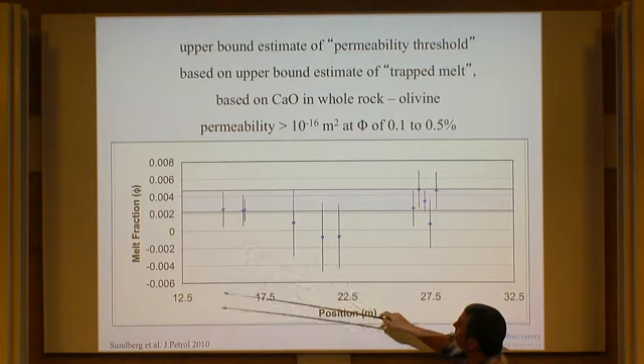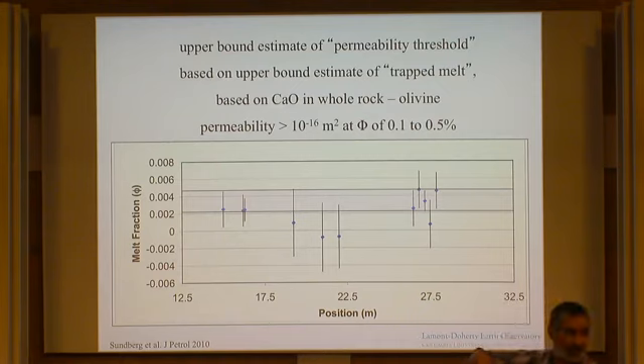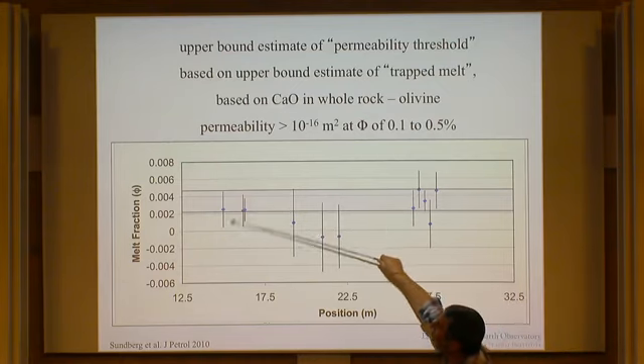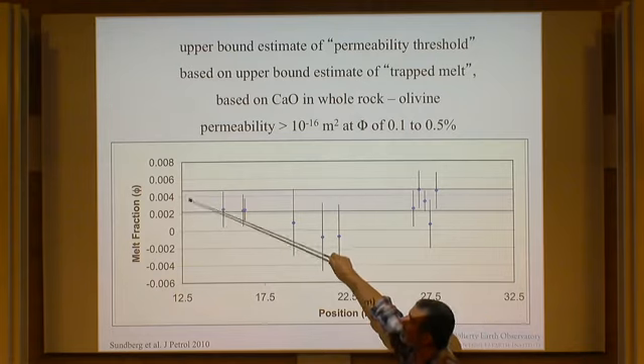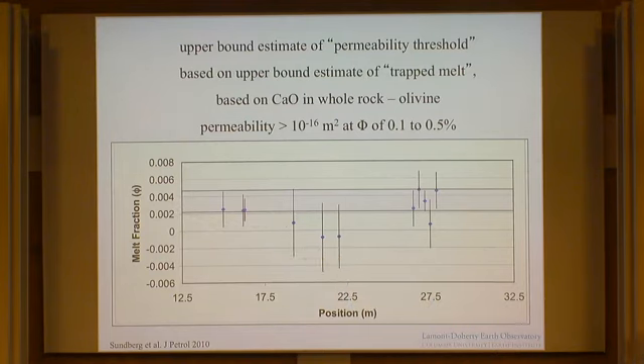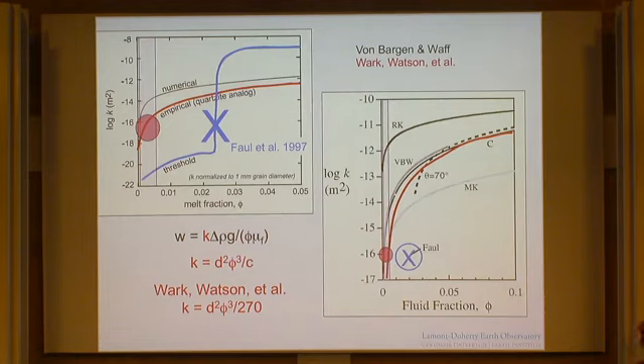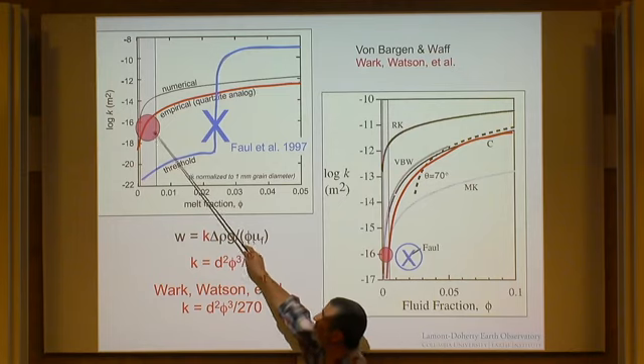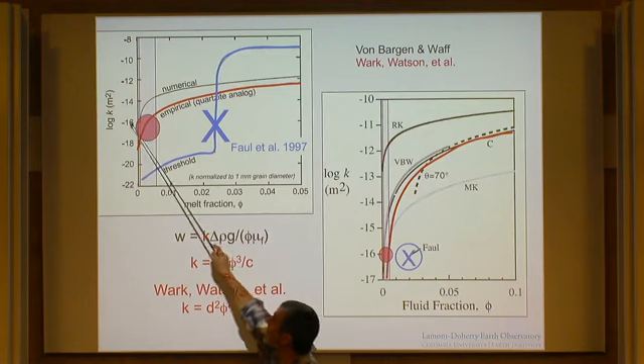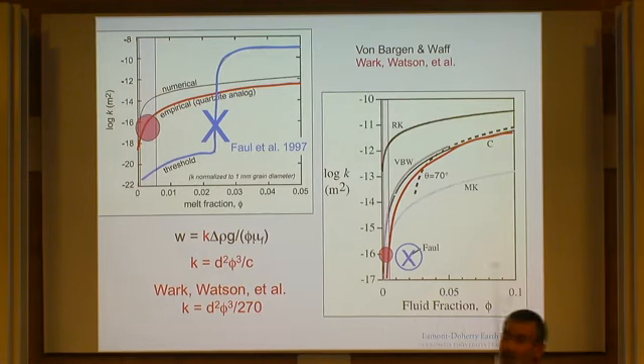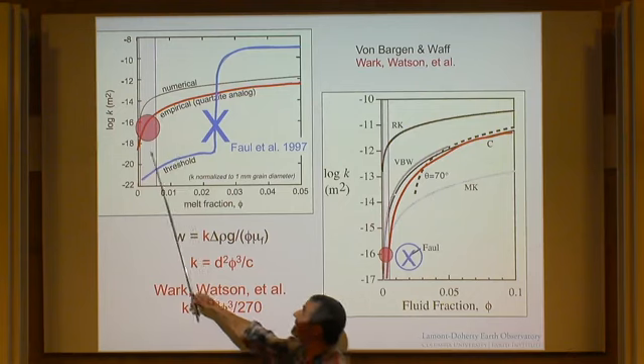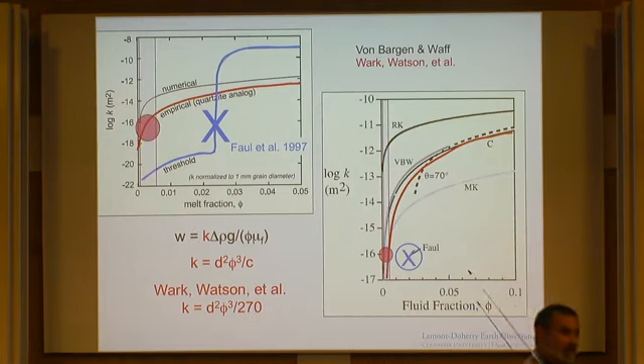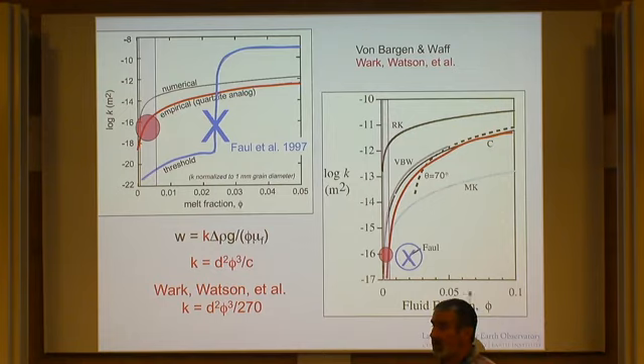And you see that it could be 0. You can get some negative values, but they're uncertain. And so it should lie somewhere between, let's say, 2% and 0.2% and maybe 0.5% as a maximum. The first thing we can say is that the empirically derived permeabilities from natural rocks have to be greater than 10 to the minus 17 or 10 to the minus 16 meters squared at these low porosities, and therefore this idea that wetted grain faces make a big difference to the permeability is not correct. They might be wetted grain faces, they might matter a lot for attenuation and rheology, but they're not making most of the melt is in these almost tubular pores, so it doesn't really matter.